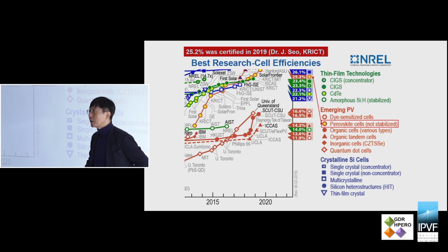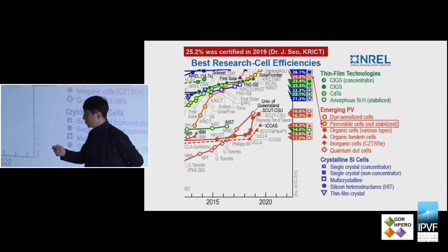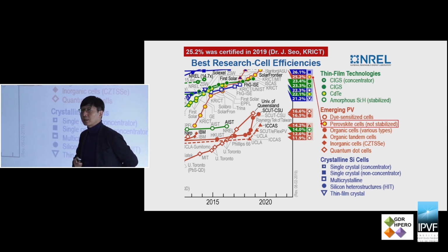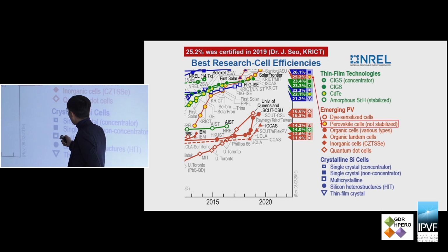It takes more than 60 years to get the 26.1%. So in less than 10 years we can get the 25.2%, which is even higher than thin film technology such as CIGS or CdTe, even higher than the multicrystalline silicon solar cell. So the perovskite solar cell is a pretty promising technology.